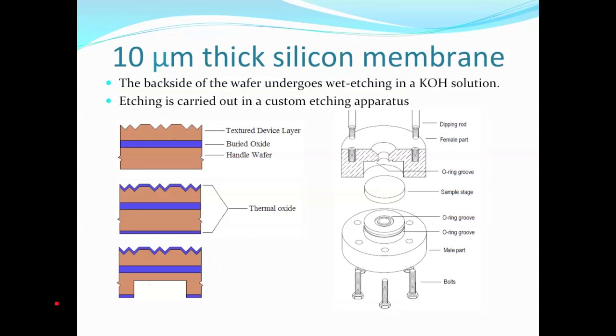By the time it gets to the handle wafer, it breaks the membrane. So what we do is we etch partially through the membrane with this apparatus and then remove it and put it into KOH and let it finish the etching. During that stage, the front side would be attacked by KOH, but we have the thermal oxide there to protect the front surface.